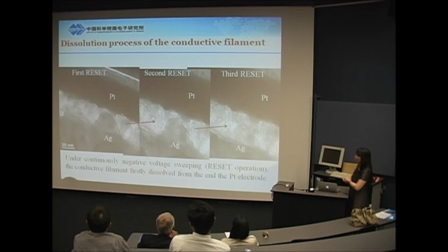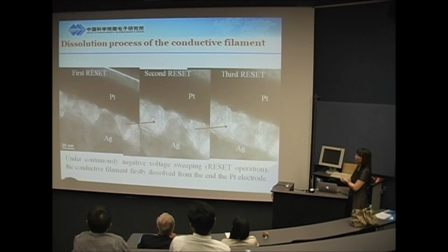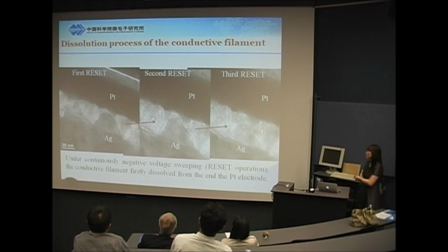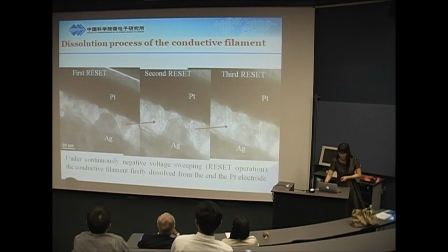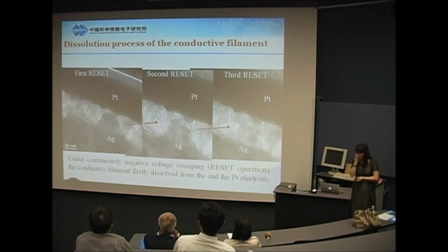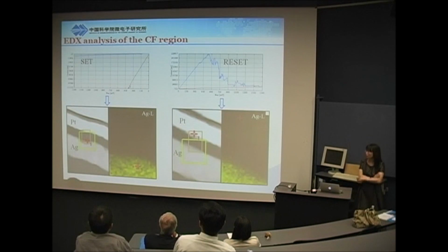The first reset just broke from here, from the platinum top electrode, by the electric field. You can see the second time this gap becomes larger. The third time is even larger. Then after several times the total filament disappeared. So this is a reset process. We are just preparing a paper and haven't published it until now. So we also did some mapping.